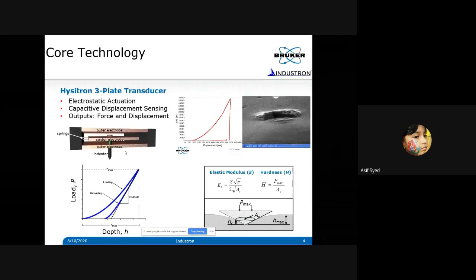So the probes are pyramidal in shape, and they are very sharp, down to like 30 to 40 nanometers in diameter, and they are made of diamond. It's a very hard material. Okay, to apply the force, you need a transducer, and there are various ways of doing it. The best way is by electrostatic force actuation.